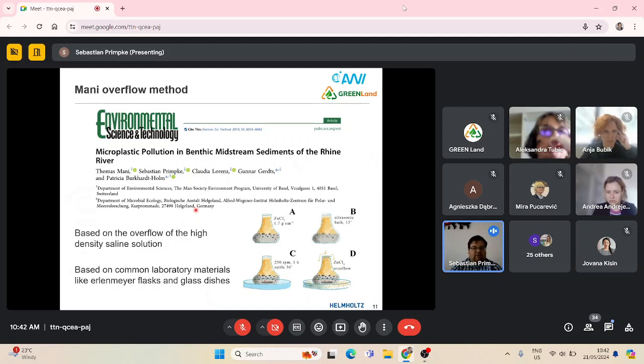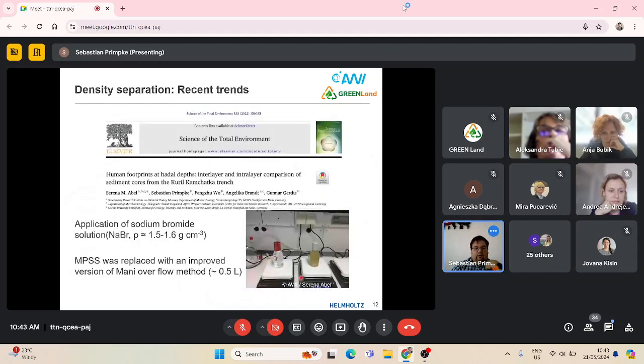So we had a joint publication with Thomas Mani and the University of Basel with Patricia Burkhardt-Holm, on how we can simplify this process. So we changed to Erlenmeyer flasks. Much easier, every laboratory has them, and we could simply put the sediment inside, sonicate it a little bit, then stir it for 1 hour and let it settle, and then add more of the solution and collect all our particles as an overflow onto a normal glass dish, and then filter it on a stainless steel filter and use it for data analysis. So it saved us quite some time and also a lot of